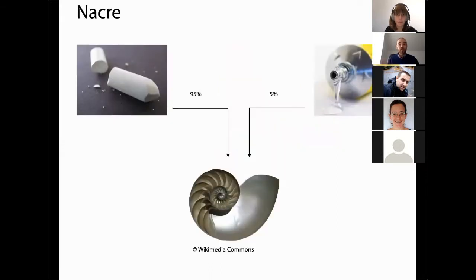So as I said, nacre has been extremely studied for probably 30 years now, because of this very high toughness. If you look just in terms of composition, you have 95% calcium carbonate, which is basically chalk. So it's a very weak mineral, with 5% of a protein that serves as glue inside.